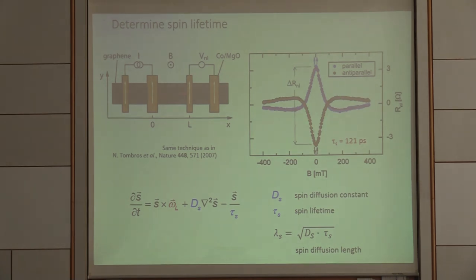For this particular example here, which was really in silicon oxide, similar made as the one in Groningen, there's 120 picoseconds, so it's a small number. I will show you now that we can do better.